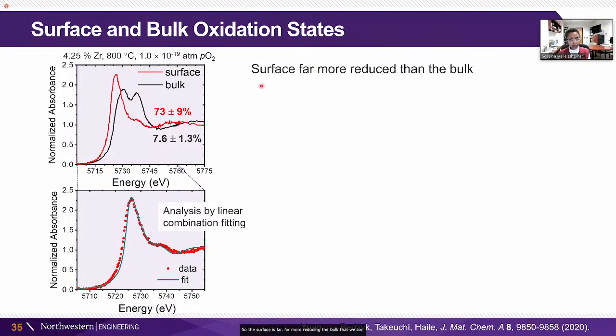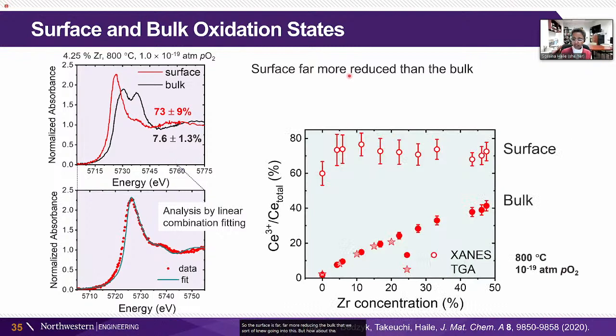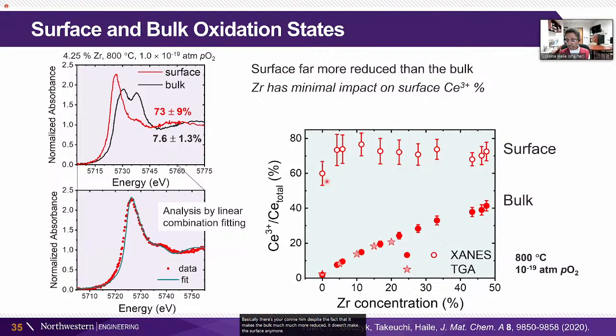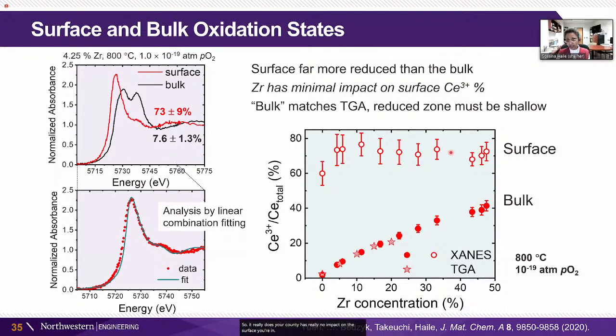That we sort of knew going into this, but how about the influence of zirconium concentration? Well, this came as a real surprise because there is none. Basically, the zirconium, despite the fact that it makes the bulk much, much more reduced, it doesn't make the surface any more reduced. And in fact, this measurement we did on a separate day, and I suspect that we didn't have the same control on the gas atmosphere as we did here. And that's the reason that this is a bit of an outlier compared to the others. So the zirconium has really no impact on the surface cerium 3+ concentration.